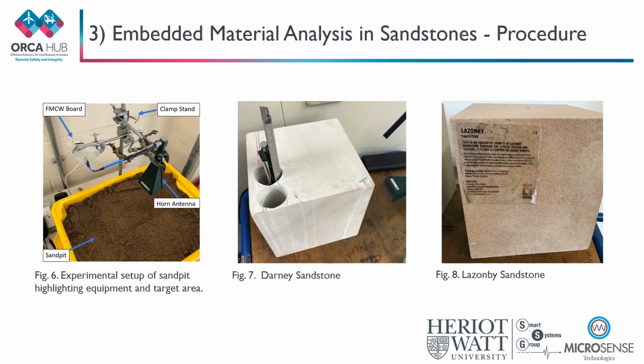The previous experimental setup in Experiment 1 was utilised again to determine if the FMCW sensor was sensitive enough to detect and distinguish between porous structures such as sandstone, which are embedded within the sandpit. Due to the limited depth of the sandpit, the experiment was constrained to a layer of sand which measured 3 cm on top of each sandstone. The Darney sandstone and Lazonby sandstone were buried within the sandpit where the return signal was compared for each.